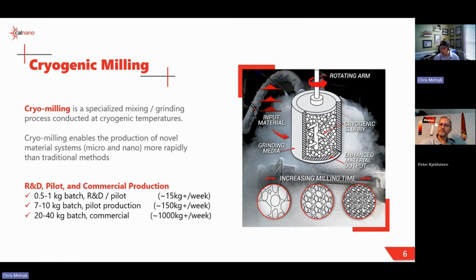And so as that milling is happening, depending on the type of material, different things will happen. But here we can see, if it's a brittle material and it's a large particle, it's going to break down because it's just brittle. But if you do this not cryogenically with, say, a soft alloy like aluminum, it's going to cold weld. All that material is going to weld itself together and gum up. And so the cryo helps embrittle it. And then we also use some process control agents to further prevent the material from over-agglomerating. And that's actually when you start to get the refinement of the grains.